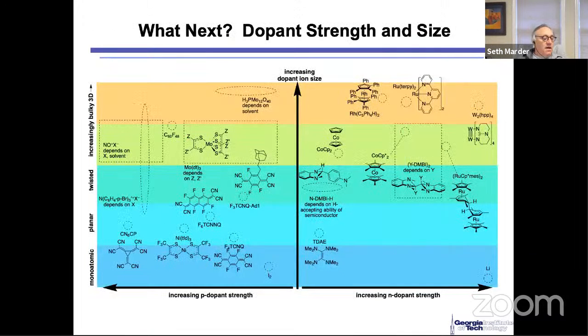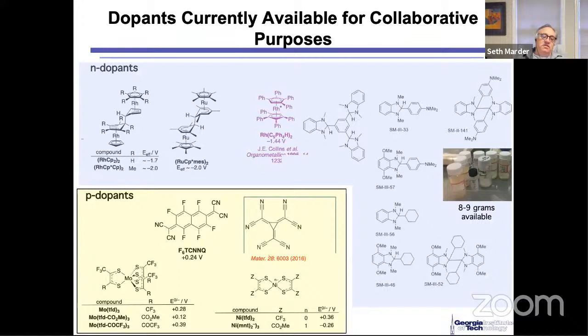Okay. As a notice, here's a kind of a zoo of dopants that have been made. I can tell you that this has been made by Adam, I think, Moulet. A lot of these have been made by us. This is a dopant that's been reported in the literature. We've made this on gram scale and have it. It's an effective dopant. It's not very soluble, okay? All of these dopants here, we have, and they're available to people for collaboration. Okay, so on this slide I show these are dopants that our groups has made. I said there were 8 to 9 grams available. That slide is old. There's on the order of 15 grams of this stuff available.